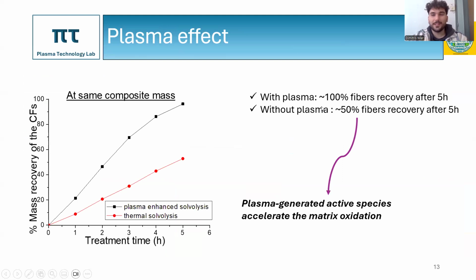Now, when we started this research, the first thing that we needed to test was how plasma affects this process. That's why we decomposed the same composite mass in two different ways. One batch was carried out with plasma-enhanced solvolysis, and the other one with just thermal solvolysis. We saw that with plasma, almost 100% fiber recovery can be achieved after 5 hours, while without plasma, only 50% fiber recovery can be achieved after 5 hours. Thus, we concluded that plasma makes this process effective because the plasma-generated active species accelerate the matrix oxidation.